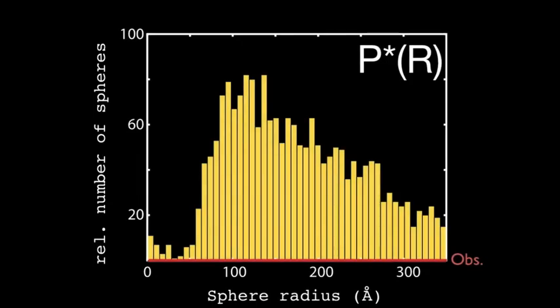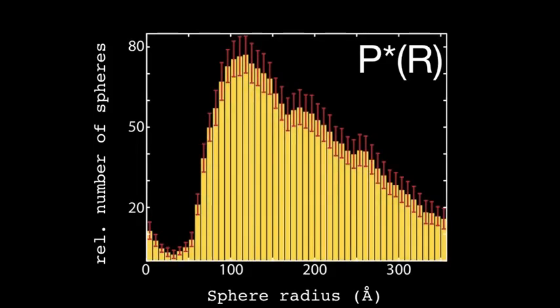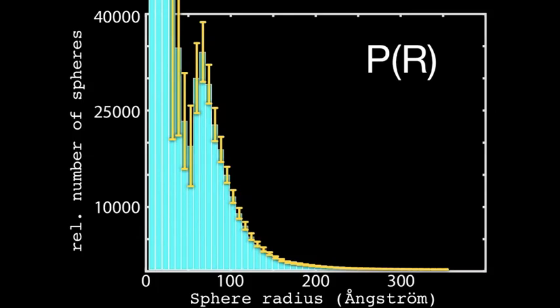When we do Monte Carlo methods with this pseudo distribution it is properly quick — this solution I can get in seconds, whereas previously it could take up to several minutes. Since it is so quick, I can repeat this about 200 times to get nice values for the means and standard deviations. This is the pseudo size distribution scaled with r to the fourth power, so if we remove that scaling we get the normal number-weighted size distribution back, with error bars on both the standard deviations and the means.